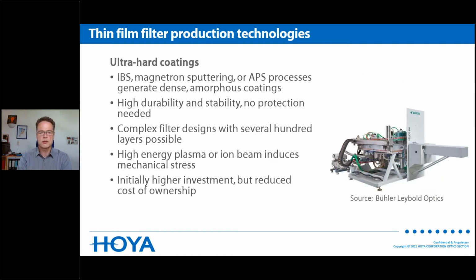And the most modern filters since 10, 15 years are what I would call ultra hard coatings. They are produced with IBS or ion beam sputtering, magnetron sputtering, or APS processes that generate very dense and amorphous coatings. These have a very high durability and stability. No protection is needed for these filters. And you can produce very complex filter designs with several hundred layers nowadays. So we have recently seen advanced filters with 300 layers on each side, which was not possible just several years ago. But also that comes at a cost.